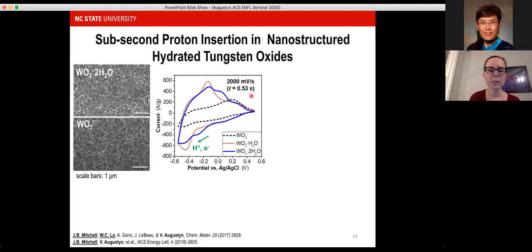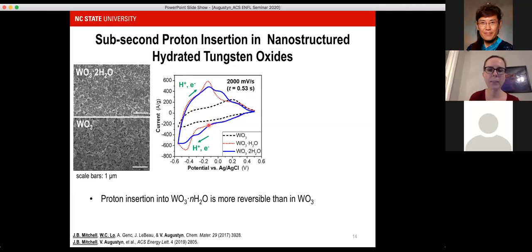What we observe is that when the current is negative, that's due to proton insertion. When the current is positive, that's due to proton deinsertion. And what we see here is, first, the area that's bounded by these different curves is different, and that has an impact on the capacity, as I'll show in a second. But the other thing is that the reversibility of the electrochemical insertion process, meaning the potential separation between the insertion and the deinsertion, is much, much less in the hydrated material than in the anhydrous material, which is starting to look more and more tilted. We say that it's starting to look more and more resistive.